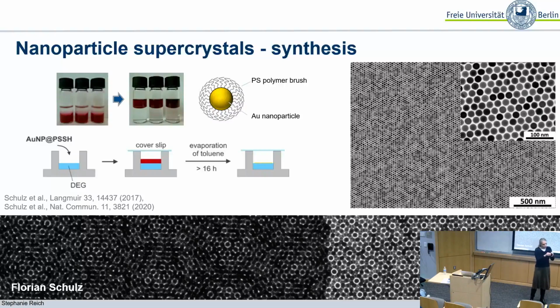So if one thinks about small nanoparticles, then they have facets, like I discussed today. But if you go to these very large gold nanoparticles, and 50 nanometers might not sound large, but for nanoparticles it is very large, then they're really perfectly spherical. But you can still see the difference in contrast because the atoms are arranged differently when you look through. The second question: if I deliberately create an edge dislocation here,